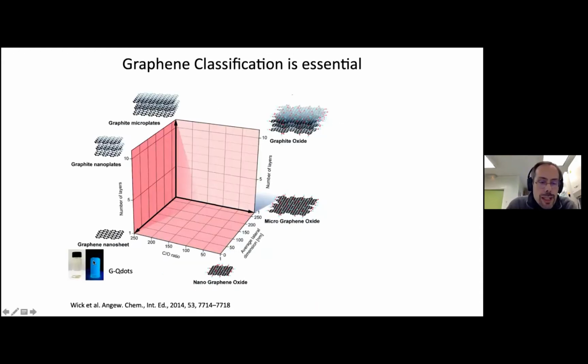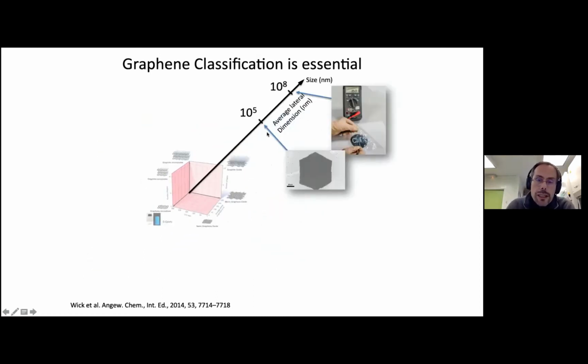In that, for example, you have graphene quantum dots that can be very useful to making labeling of cells, for example, due to the optical activities. In our case, we are talking of graphene of very large size, one monolayer and without oxygen. So it's on this axis, very far away out of this graph, because we are dealing with large crystal of graphene produced by CVD of graphene on copper, and which are transferred on a polycrystalline element on polymers. I'm going to speak a bit how we make that.